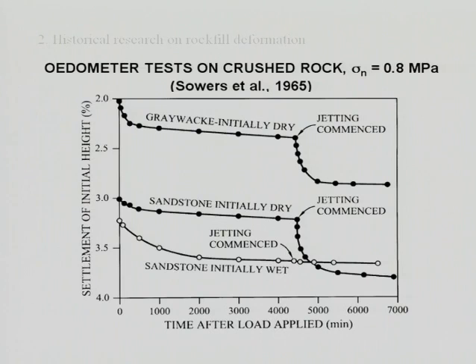I will simply show a couple of slides on relatively old work. This one, the oedometer test on crushed rock, and you see what happened. You have an oedometer, you load your sample, eventually it comes to a rest, to a relatively small rate of deformation. If you wet your sample here, there is a sudden acceleration, and again it comes essentially to rest. Now this is for this material. You change the material, similar type of behavior. You see that if you compare the deformations after wetting with the sample that was initially wetted, you more or less get the same result here. And this has been checked again and again by different researchers.